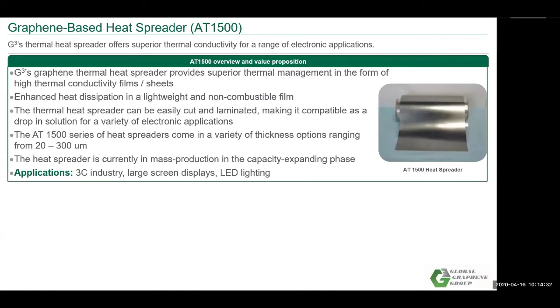One of our key products is AT1500. This film was developed specifically for 5G technologies. We know that in the future 5G is going to be the dominant technology for cell phones, electronics, and transmission communications, so we started early to develop something different from the traditional product. It is a dense film, with a density of around 2.0 ± 0.2 grams per cubic centimeter, and it offers 12 to 15 watts per meter per K in-plane thermal conductivity.